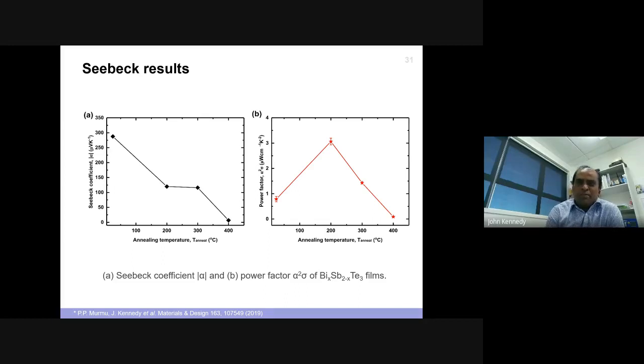Then the simplest way to estimate the thermoelectric efficiency is the power factor, which is basically alpha squared sigma. If you see the power factor, by annealing somewhere between 100 and 200 we actually get a high power factor, which can relate to the efficiency as well.